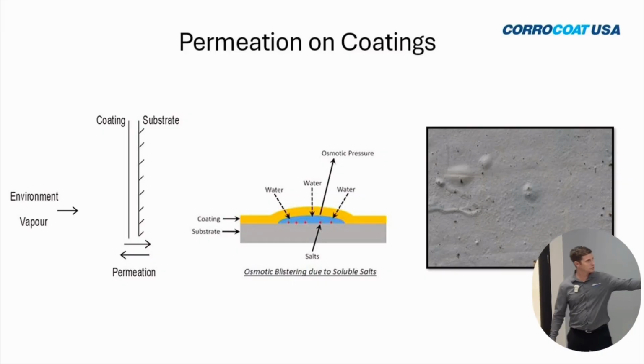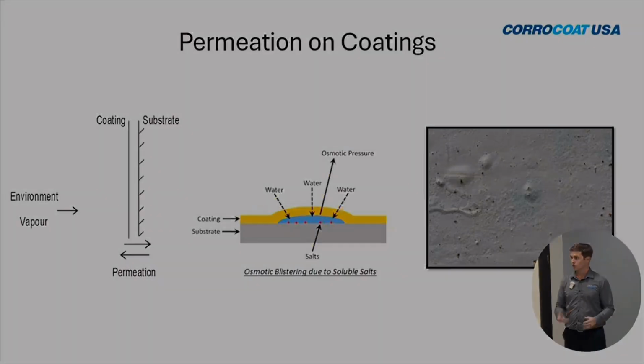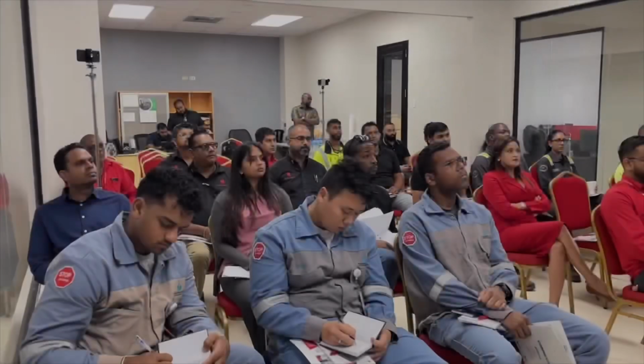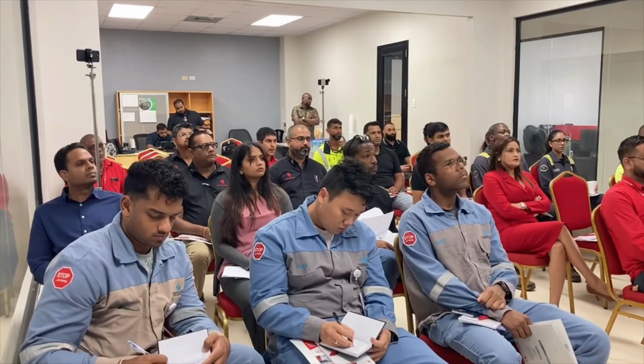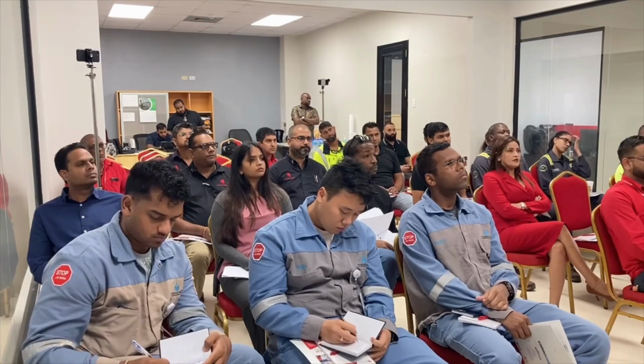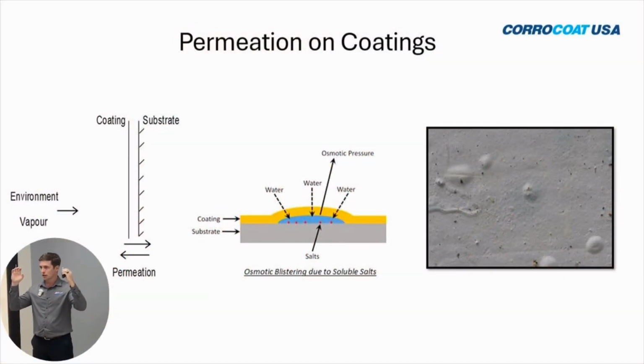Practically, as you can see here in the picture, whenever you're looking at fabric maintenance or internal linings, over time you may see permeation through the given coating film, which will allow moisture or other corrosion-causing ions to get through the film and to the substrate. It starts to corrode, you get a bubble. Now the reason that happens is because you have a tendency towards permeation. When you have a film in between differential pressures, gas is going to want to try to fill that void. That's the natural phenomenon that we're fighting.